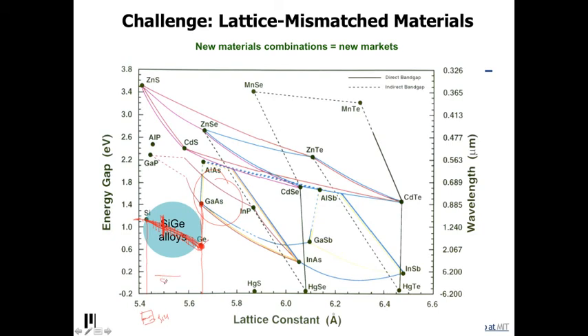So you would have sort of the silicon wafer. The magic that we did was relaxing this so it's at its equilibrium lattice constant and not have too many defects come up. You could put silicon back on top again, but because this had been relaxed to its larger lattice, then this one would be strained because it wants to be smaller, right? And so that actually causes the electrons in here to move faster. And that was actually, at the end of the day, an experiment to tell management that this was all important, but indeed it became the most important output itself.